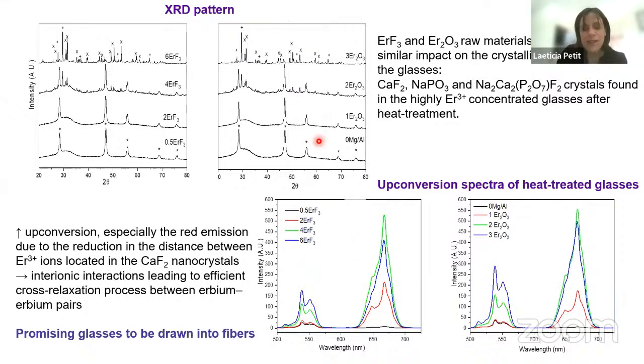And so this confirms that even if we have a small amount of calcium fluoride crystal in these glasses, the erbium is still going inside, and then we have a lot of this green and red emission. And the red emission is higher than the green as compared to the glasses prepared with a low amount of erbium, and we think it's due to this interionic interaction leading to an efficient cross-relaxation process between the erbium-erbium pairs. But the glasses with high concentration of erbium are actually quite promising, and we are now in the process of drawing them into fibers.